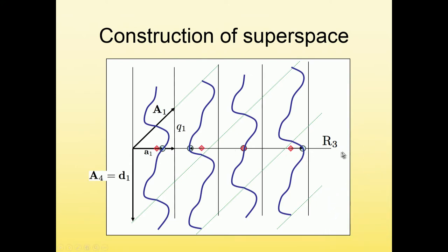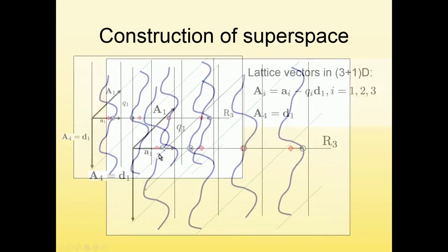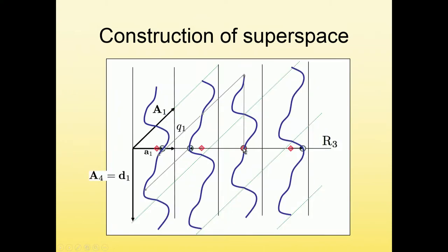The original structure had no periodicity, the new mathematical construction has periodicity. And that means that we can map all the atoms from the whole structure onto the first unit cell because of the periodicity. For example, this atom has its equivalent in the first unit cell by shifting one periodicity up and two periodicities against A1. And we end up here. So this atom has its counterpart at this position of the unit cell.